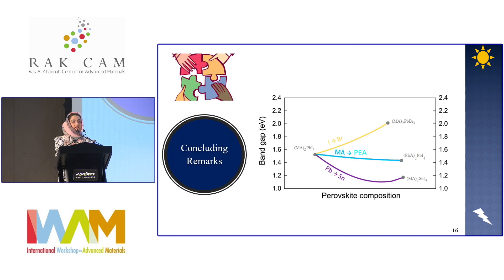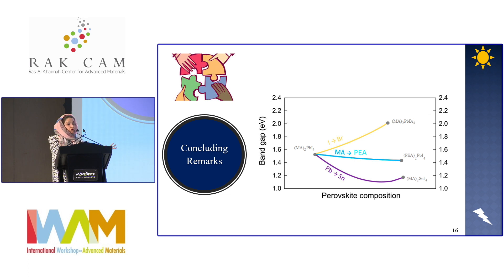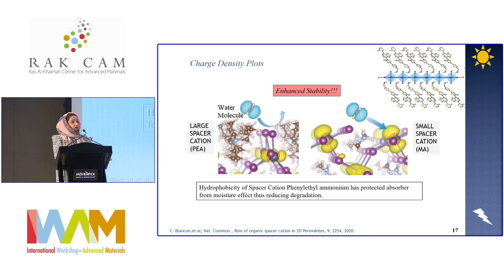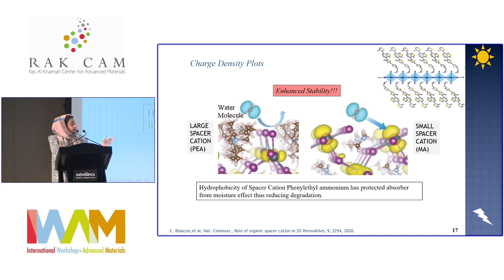The final concluding diagram shows the effect of doping different elements: replacing lead with tin or germanium reduces the band gap; replacing methylammonium with phenylethylammonium slightly reduces the band gap since this affects size and shape rather than chemical activity; and replacing the X site with smaller halides — iodine with bromine or chlorine — increases the band gap. I also performed molecular dynamics calculations introducing water molecules to study stability, showing that the larger spacer cation protects the chemically active octahedral cage from water attack, so stability is achieved.